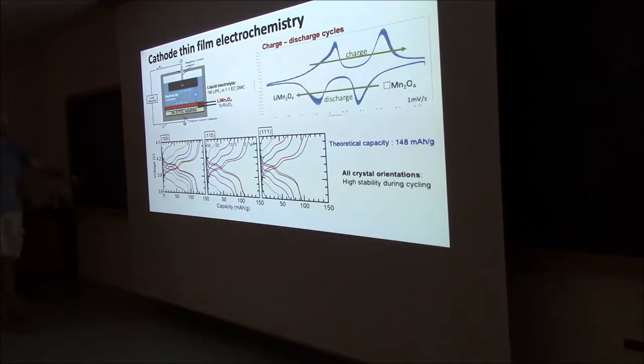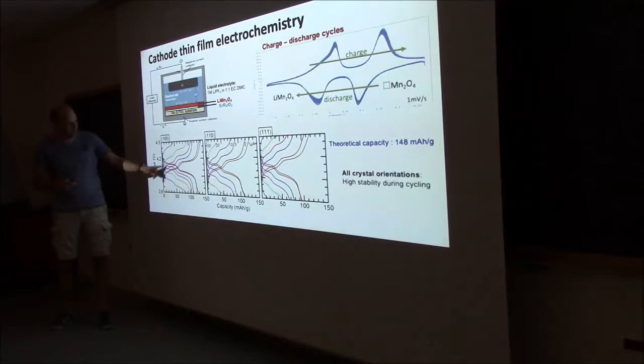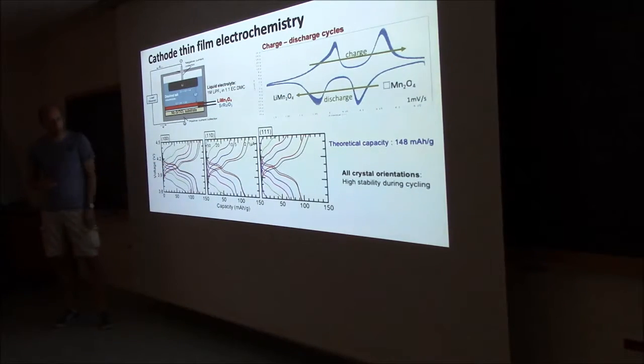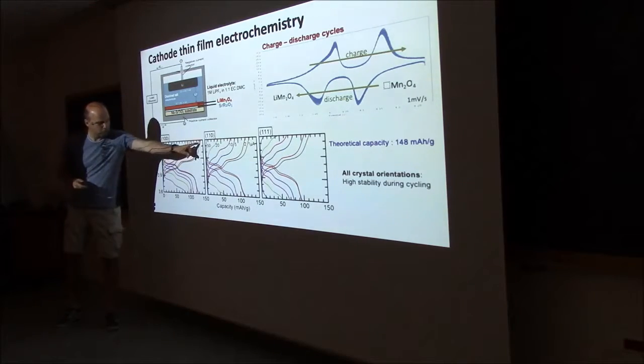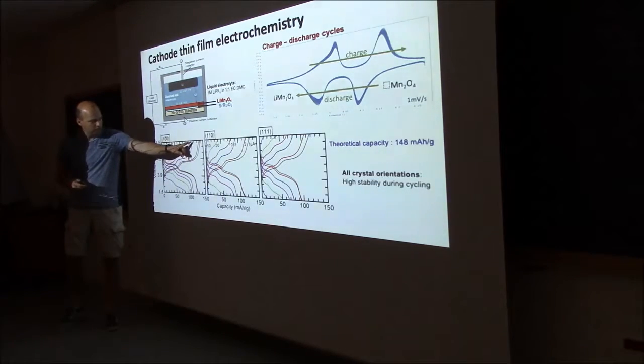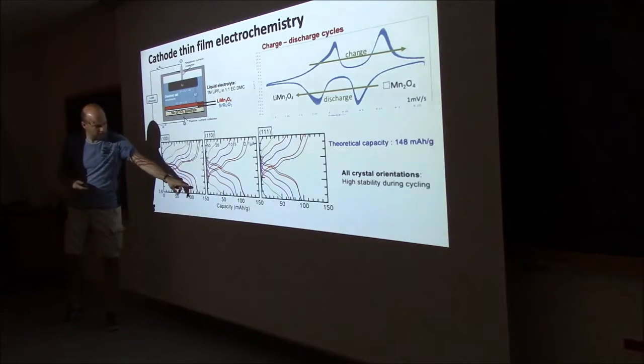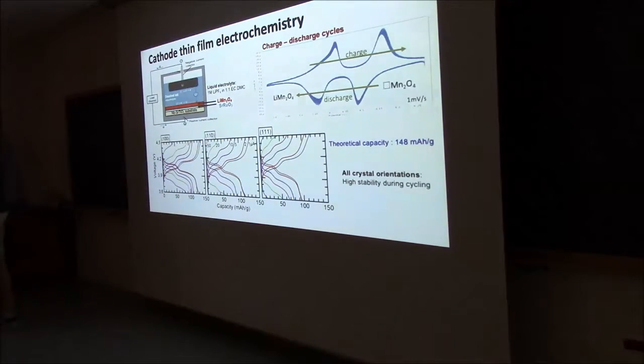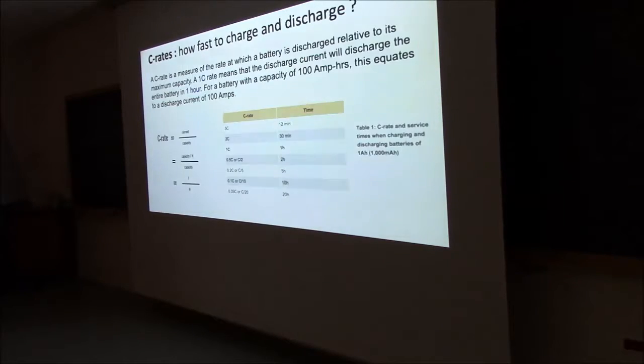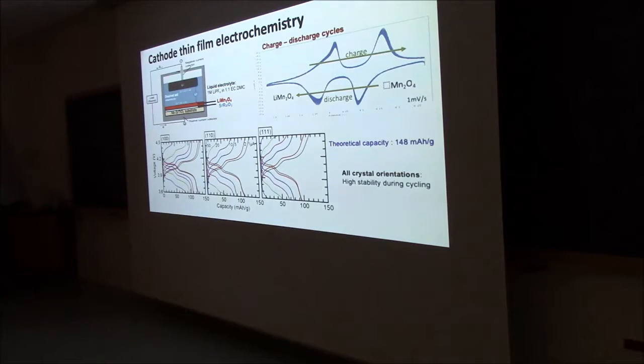So what you can see here is that things are being charged with different rates, so different currents. This is slow, so you get more capacity in than when you do it faster, then it drops, and this is during the discharge. And for the 3 orientations, from this picture you see that everything is working pretty well. Now, if I talk about fast and slow, I'm not sure if you've seen it. Yeah, sure. I have a question from the previous. Sure. Just curious. You have the peak where you said lithium is being taken out. Is it possible to tune this?